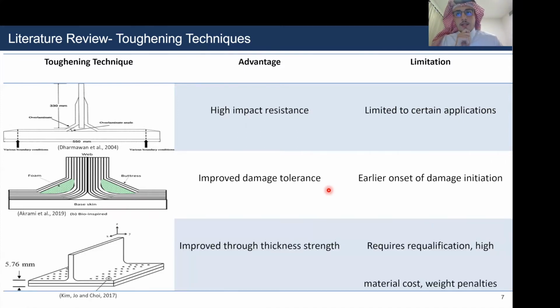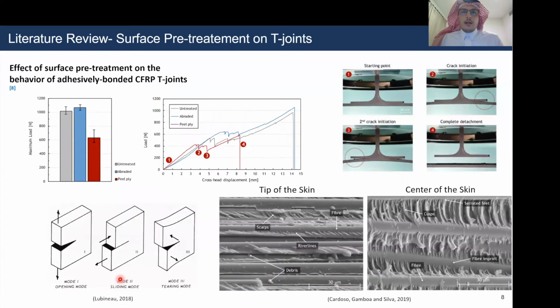A third toughening technique is by using stitching or Z-pinning. So pins or stitches are placed to improve the through-the-thickness strength in between this interface of the skin and this stiffener. However, this requires requalification and high material cost and can incur weight penalties. Another toughening technique, which is not mainly modifying the structure of the T-joint, but rather the adherends themselves, is applying a pre-treatment on the adherend.